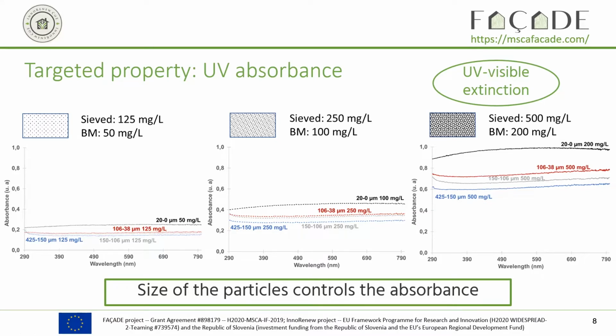And you can see that first, the absorbance is dependent on the concentration. And there is a linear relation between the absorbance and concentration of the solution. And then that the smaller the particle, the higher the absorbance. When we got to the ball milled particles, they were so small compared to the others that for equal concentration, we could not compare the absorbance. So here on the 3 different graphs, for the ball milled particles, the concentration is more than 2 times lower than the sieved ones, and the absorbance is higher for all the different concentrations. So what is controlling the absorbance is the size of the particles.